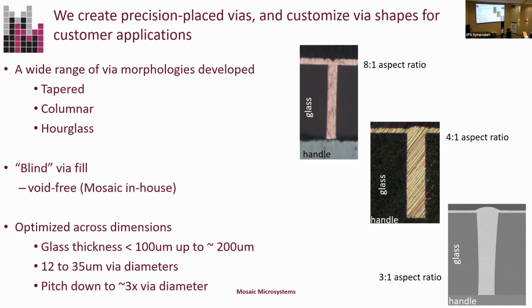We have dealt with glass that's thinner. As you get down to 50 micron thick, did I say millimeters? Yeah, I throw factors of 1,000 around like they're nothing. So we actually deal with 100 micron thick glass and up to 200 micron thick, which is the regime where a handle really makes a difference. By the time you get up to 300 micron thick glass, a handle is much more optional. It's easier to handle on that.